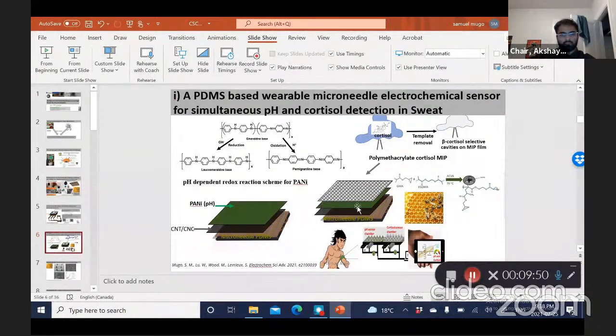We use exactly the same base, microneedle PDMS, printed with carbon nanotubes and cellulose nanocrystals. Again, we are using that mainly as a binder, so that the carbon nanotubes can print as a very, very thin film. And then we integrate again the polyaniline, as you're going to see, as a conductive polymer, so it increases the conductivity of the entire platform, despite the fact that you're also using it as a pH chamber. And we integrate on top of it the polymethacrylate cortisol molecularly imprinted polymer.